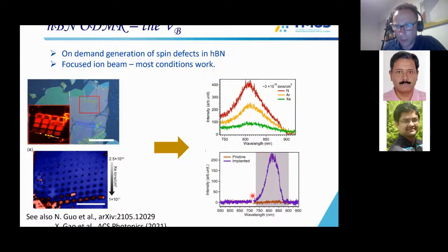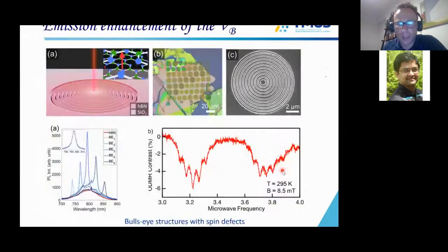And you can see this, we can induce this emission very efficiently. And then we can bring both walls together and make a cavity out of hBN and then induce the boron vacancies right in the middle. So we made a bullseye structure, just the easiest cavity you can make from hBN. So you can see here an array of many different bullseye structures.